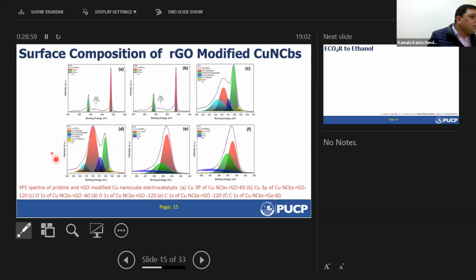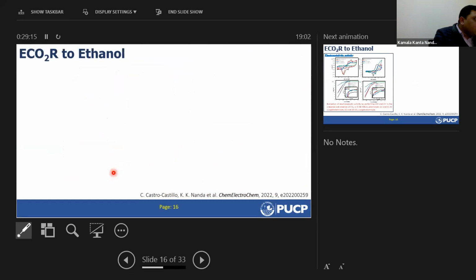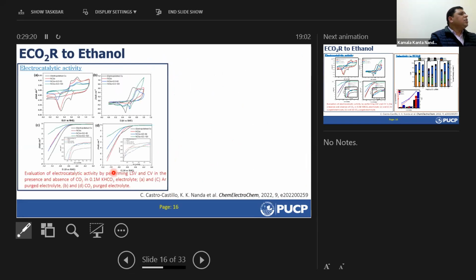The main thing in this slide to look at is that there is a charge transfer from RGO to the copper surface, and therefore we are getting a copper-oxygen signal here. This shows that we have a subsurface oxide layer in the electrocatalyst, which is helpful in ethanol production. And we did the normal electrochemical characterization.